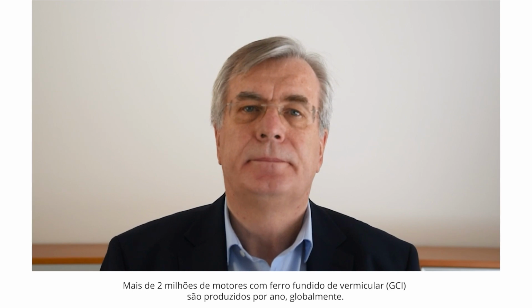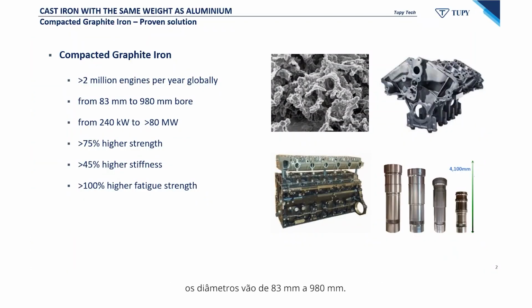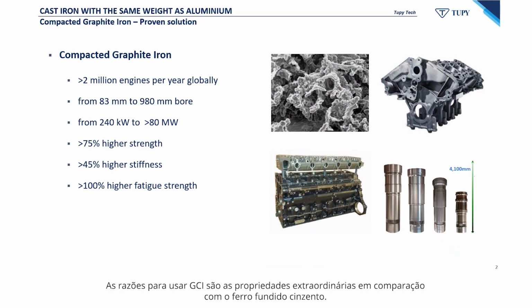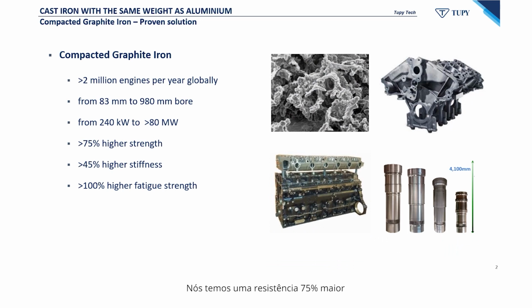More than 2 million engines with compacted graphite iron are produced per year globally. The bore reaches from 83 mm to 980 mm and the power output from 240 kW to more than 80 MW. The reason to use CGI are the extraordinary properties in comparison to grey cast iron. We have more than 75% higher strength, more than 45% higher stiffness and more than 100% higher fatigue strength.